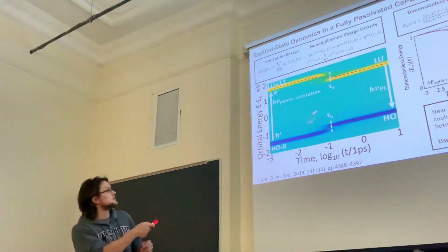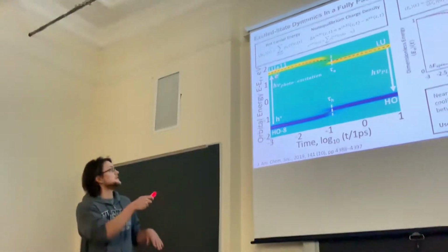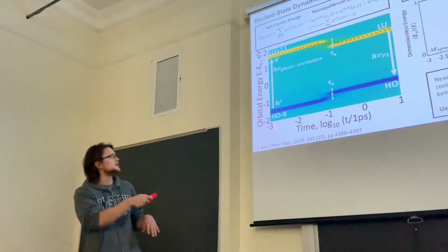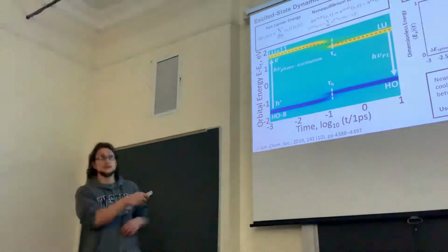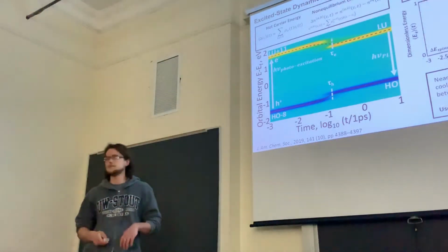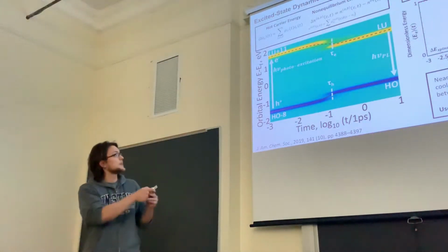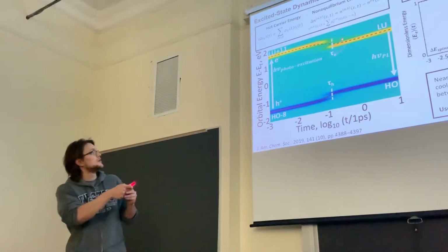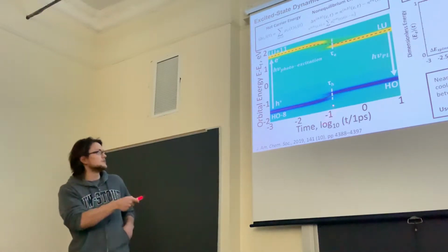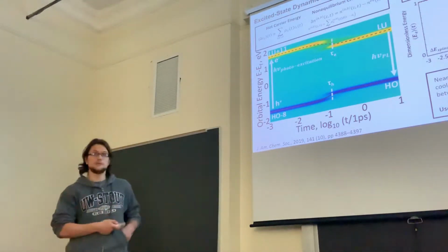The green represents charge neutral background, so just the ground state. The yellow represents non-equilibrium charge density, so you have a photoexcited electron, and blue represents hole density at these energy states, and the lines just correspond to energy expectation values due to changes in population over time. And so for both these models, we see fairly fast hole cooling. It occurs on 100 femtosecond time scales, and that's in line with what they see in experiment.